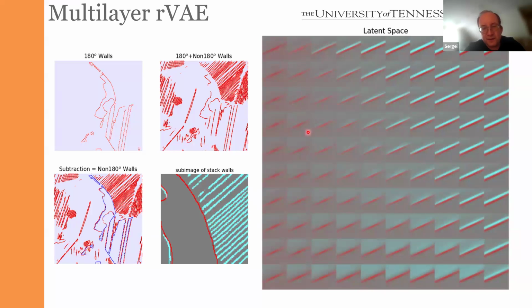So you see here that in this part of the latent space, the red lines are much weaker, and they have this funny contrast where they are very strong in the center where we took our patch. But the intensity of the red contrast decays close to the edge of the patches. So here, this is not happening. They have equal intensity across the whole line. Here it is strong in the center, weaker to the edge.